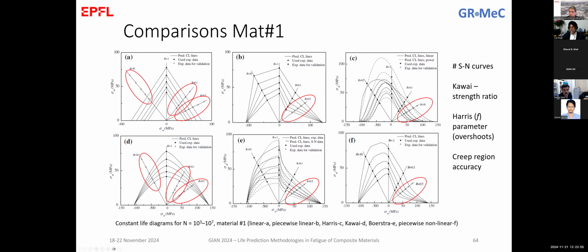For the Harris diagram, again, I used the data at 0.1, -1, and 0.5. You can see here that in this case, the diagram does not cross the data exactly because the fitting is on the entire data range. And then I predicted again here, the R equal, here is a mistake, should be R equal 0.5, not R equal 10. So I predicted this SN curve, and we see that the prediction is not so good. The same for this diagram, the piecewise nonlinear, I used 3 SN curves to predict the fourth one. And the same for Boerstra, I used the data from these 3 SN curves to predict the fourth one.